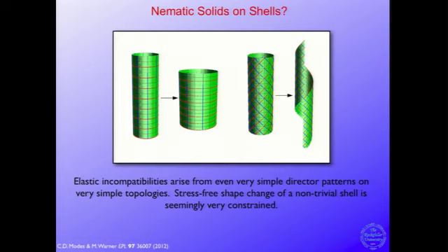And you get a large buildup of stress as soon as you tip it at all. And this is totally topological, because anywhere local, you can satisfy the strains completely. And despite that, you still get large stress build up. Stress builds up because of the winding mode of the cylinder.